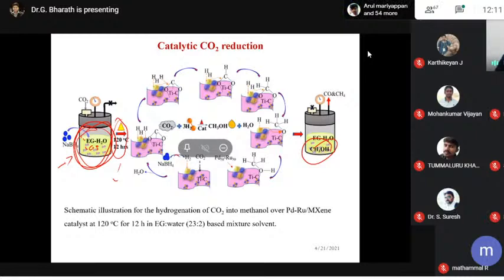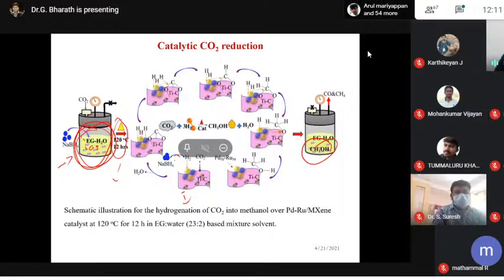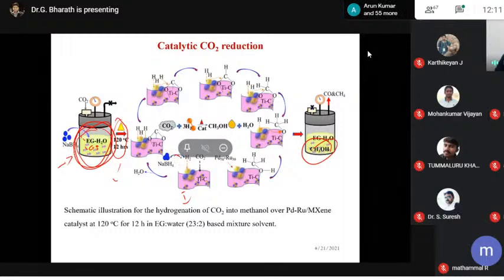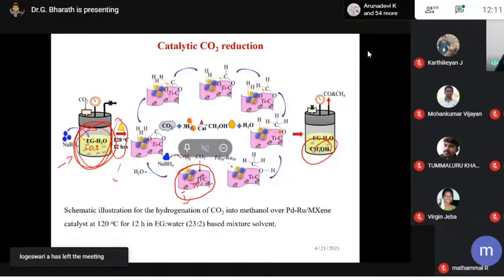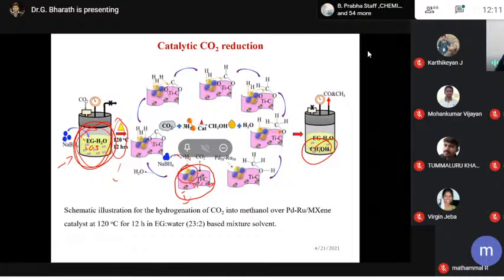This is the first step. When we add sodium borohydride, it produces hydrogen. See, this is our titanium carbide, that is the MXene sheet, and this is our material. When we dissolve sodium borohydride, it produces in situ hydrogen. Then this hydrogen easily bonds with this metal, and it forms a metal hydride.